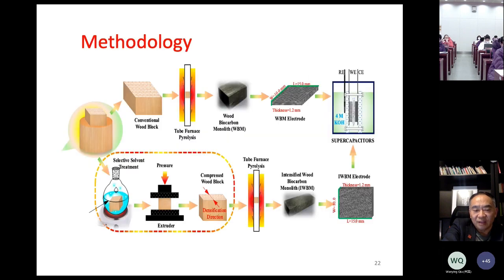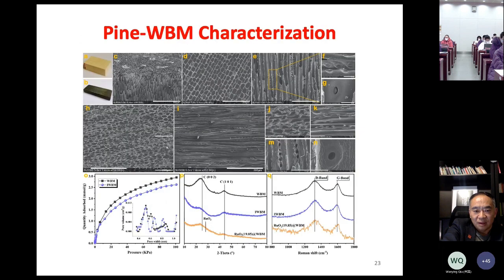Evan tried the traditional way to produce biochar, and also another way, where we remove lignin. In this case we compress it, and the purpose is to increase the density of the biochar. We call it intensified wood biochar, a monolith. So these are two different procedures to produce biochar: one is the traditional procedure, and the other is after removing lignins, so that we can compress the wood and produce high density wood biochar. Here are some results.